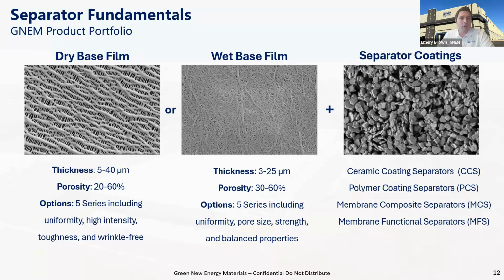We have four categories of coatings. I'll go into these a little bit in detail here: ceramic coating, polymer coating, membrane composite, and of course our membrane functional separators, where we do the coatings onto the base film. So ceramic coating series, most of what we're looking at is alumina, boehmite, and there are others in here, but these are the main coatings. It's really all about thermal stability, increasing high strength and thermal stability. That is where these ceramic coatings come into play. We have low moisture content, low thermal shrinkage, and of course they can come as small particle spheres or nanofibers. But the ceramic line is all about enhancing safety of the cell.